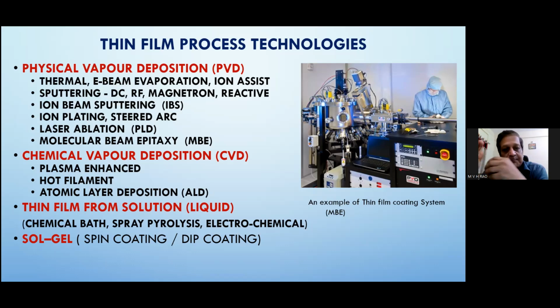So then with magnetron sputtering, what people thought was you can increase the electron density near the target by putting magnets behind it, so that the electrons move around and more ionization of the argon takes place. Once more ions are there, they bombard more, and more flux of material can be etched out and deposited. And in the same case, if you do reactive sputtering, you add some oxygen or nitrogen to the chamber in addition to the material that you are depositing. Suppose chromium is evaporated and you put some nitrogen in the chamber, then they both react and chromium nitride is formed. The reaction takes place on the substrate surface, so a chromium nitride film is formed. That is a reactive process. These are all further innovations that have come up.